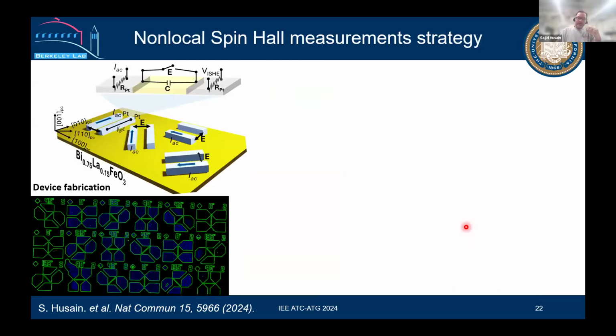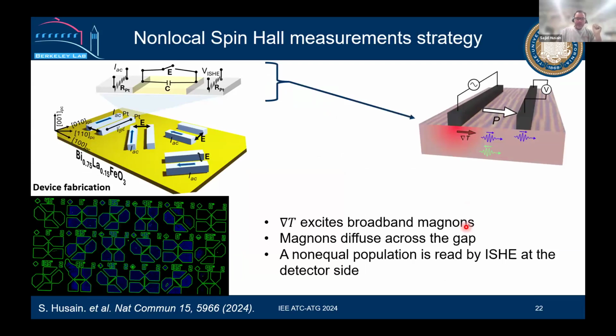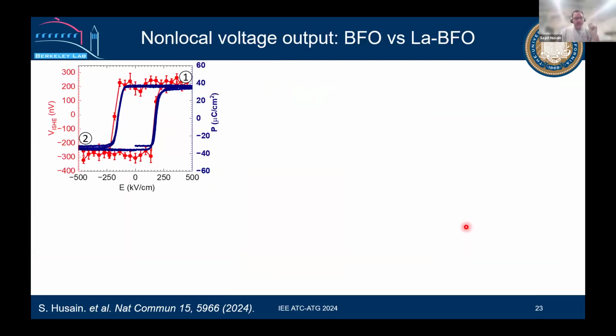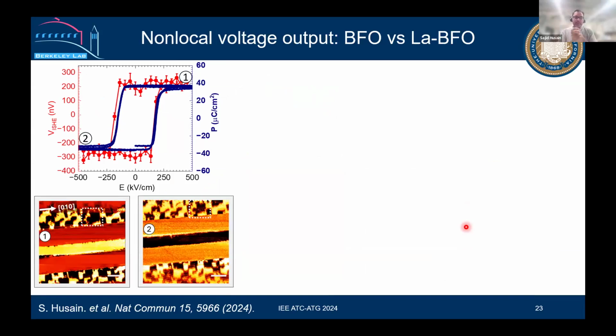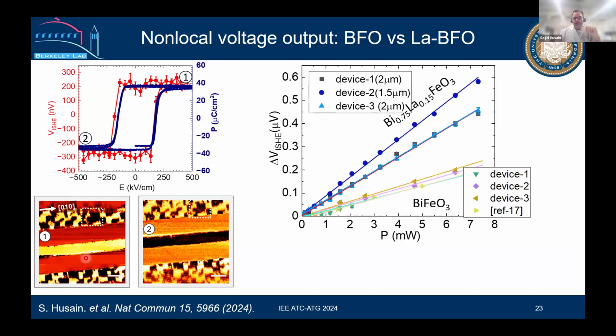But we did some experiments by putting a lot of electrodes on a sample, the same experiment, second harmonic, same data again, electric field scan as a function of the voltage output. What we see is after electrical poling, these are my platinum electrodes here. What we see in the middle of these two is a single domain, and that's the one we were looking for. And if you compare with bismuth ferrite and lanthanum bismuth ferrite, the output voltage is significantly higher, which was our main target. And that works actually.